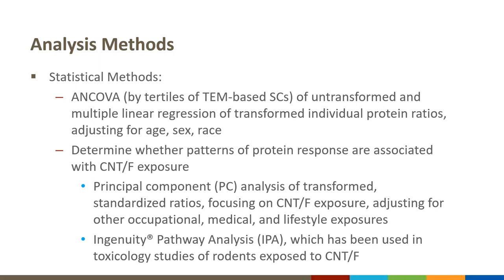We also did multiple linear regression of Box-Cox transformed protein ratios, and we adjusted the analyses for age, sex, and race, which were found to be the most predictive measures on their own outside the carbon nanotube variables. Next, we wanted to do a pattern analysis to determine whether there are patterns across the range of biomarkers that were associated with the CNTF exposure. The two pattern approaches we looked at were principal component analysis of the transformed standardized ratios. And by standardization, we reduced some of the variation in the huge responses that we saw for some of these biomarkers. It's also a typical approach used in principal component analysis.